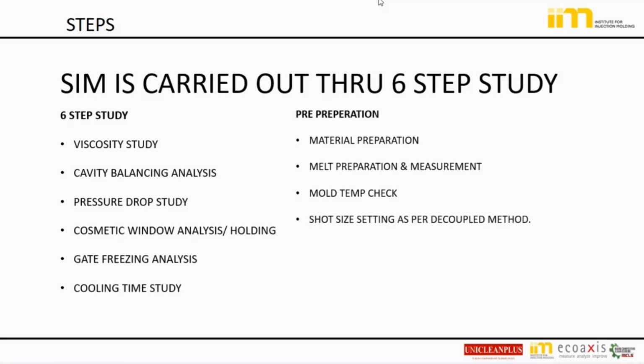And shot size: before going ahead, we have to set the shot size using the decoupled method. It means we have to inject the part 98% by injection speed. Then after injection, there is a switchover point, and we transfer into holding or packing. This is known as decoupled, separating injection and holding. To do this, we have to switch off the holding in the machine when we are taking the T0 trials. Switch off the holding, see what is happening in injection, and set the switchover point so that we are always injecting 95 to 98%.